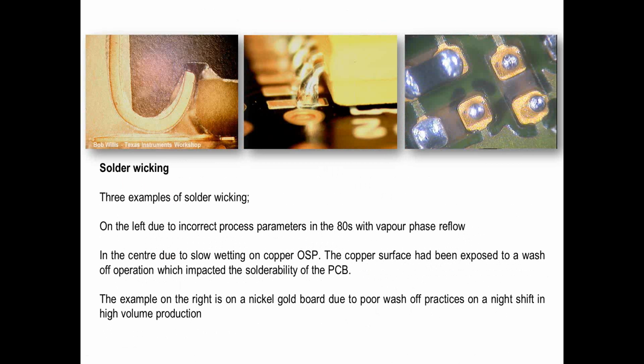If you've got a solder joint, and if the solder wants to wet the component before it wants to wet the pad, because there's a difference in solderability, then that could be a heating problem because the board is slower to heat up than the component termination, which is normally what you used to see in vapor phase. However, in two of these examples, the middle sample and the one on the right-hand side, this is clearly a PCB wettability solderability problem. So the solder has wet up the termination on the SO resistor network because the solderability of the board was affected.